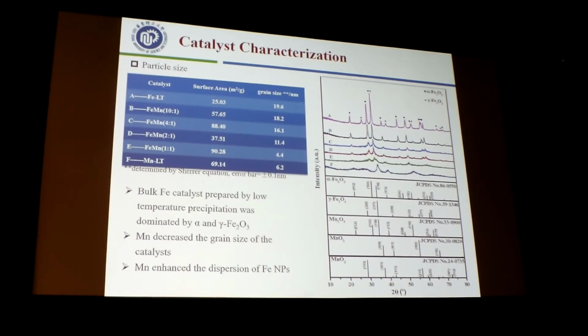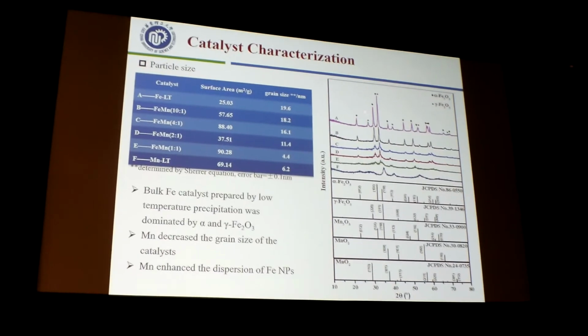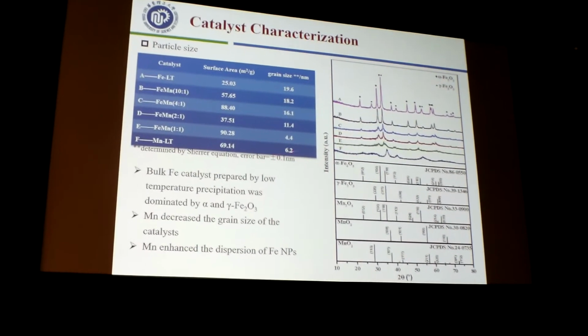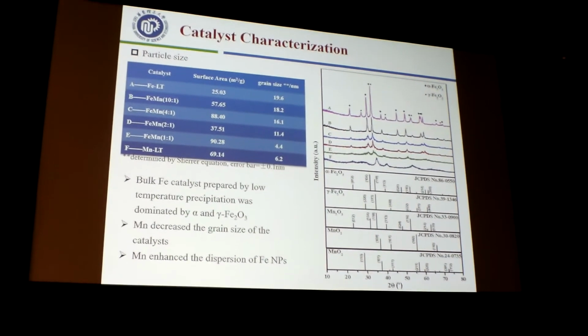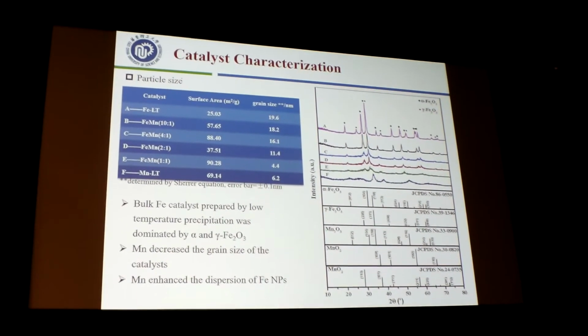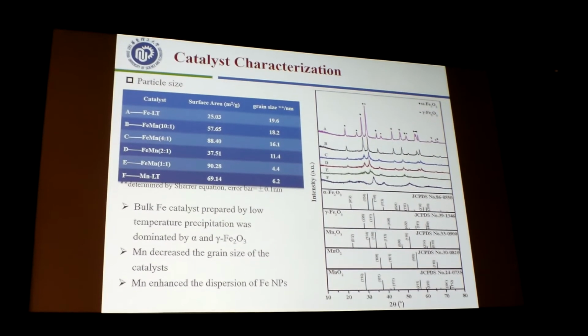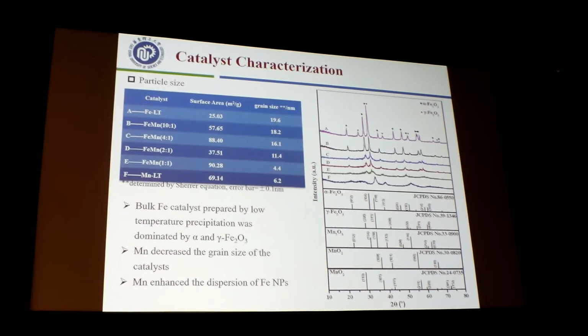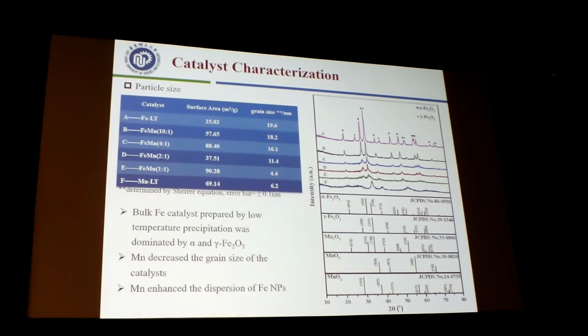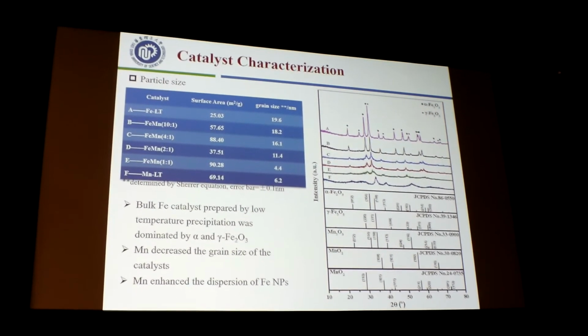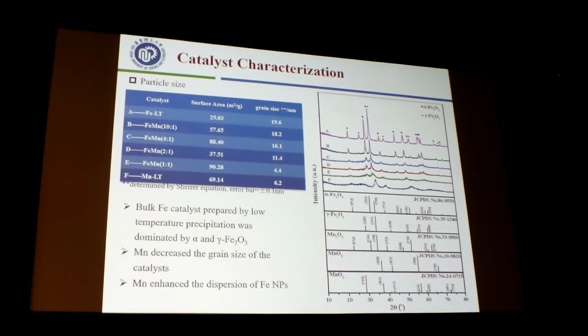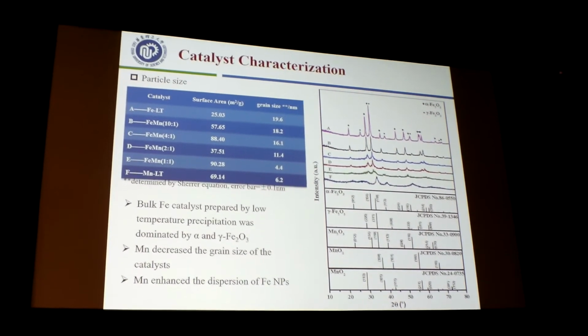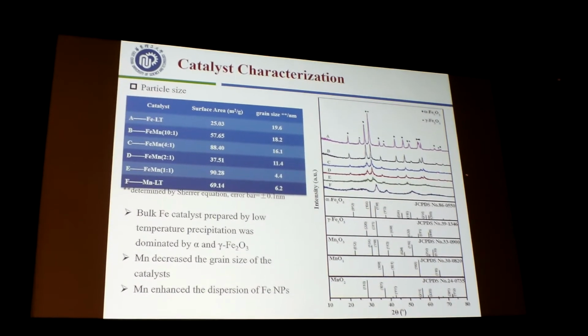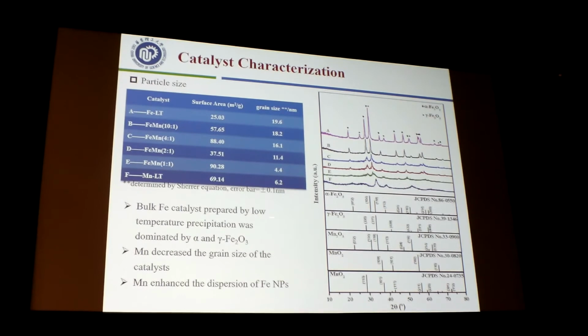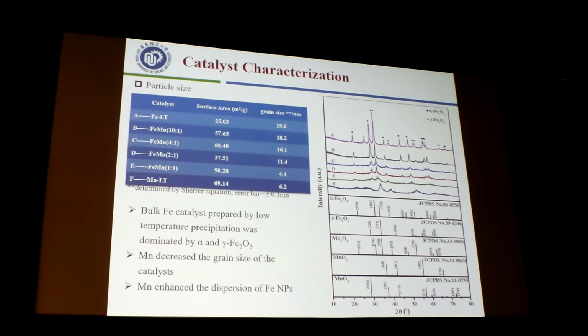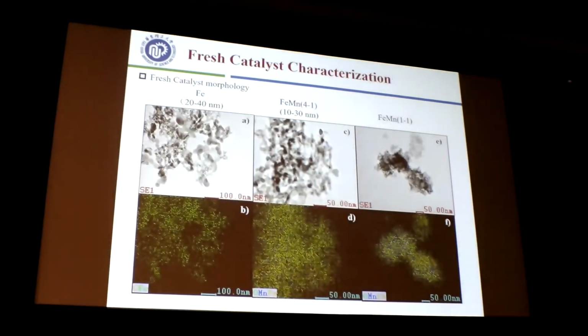From the XRD experiment, you can see that the bulk iron catalyst is characterized by alpha and gamma iron oxides. But as we increase the loading amount of manganese, the grain size of the catalyst decreases, and the intensity of the iron phases decreases, and the manganese catalyst is dominated by manganese oxide. So we can see that manganese enhances the dispersion of the iron nanoparticles.